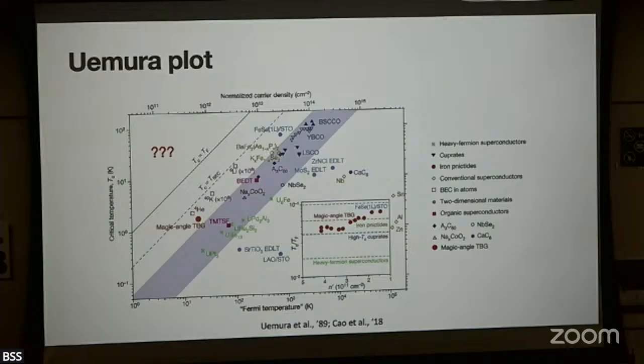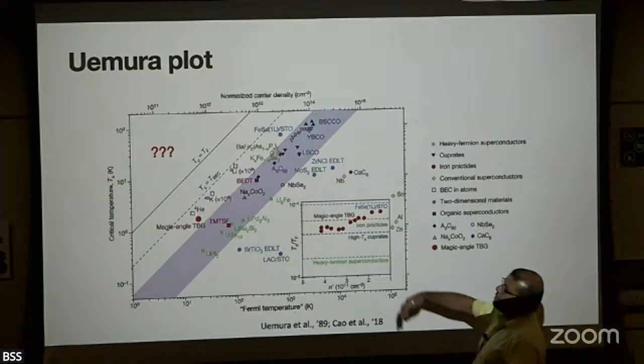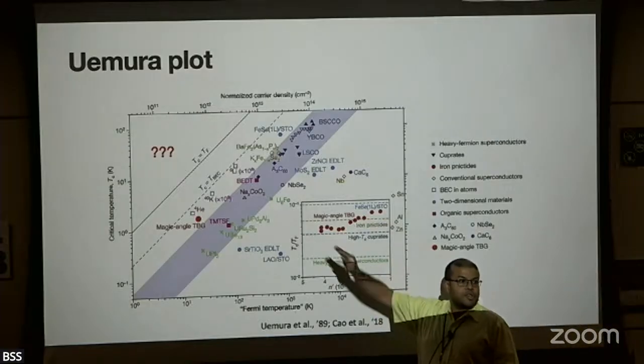So what was done to come up with this table is something quite similar in spirit. You measure the carrier density from some measurement. You measure m star, also from some experiment. And then you basically use the standard formula for a Fermi temperature that you know for a Galilean invariant system, and use that as a proxy for TF. And the interesting thing is, if you do that, everything seems to be bounded by that line, which is Tc equals TF.